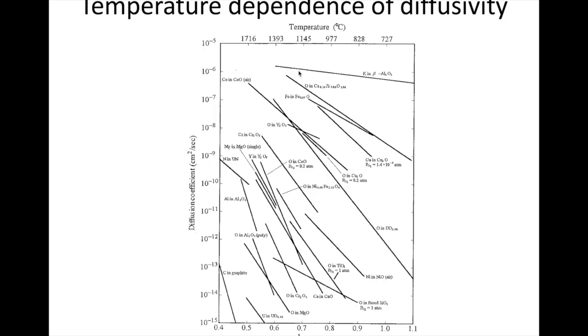And so what we see is that this expression, right, this Arrhenius relationship, because we're plotting log of the thing versus 1 over temperature, that expression is linear, right? So the slope then tells us about the activation energy, the term we just talked about, and then we can also get information about the pre-exponential as well from this curve, right? So that is what this is kind of showing. And the higher the diffusivity here, the faster diffusion will occur in that material, right? That's kind of how we're interpreting this.